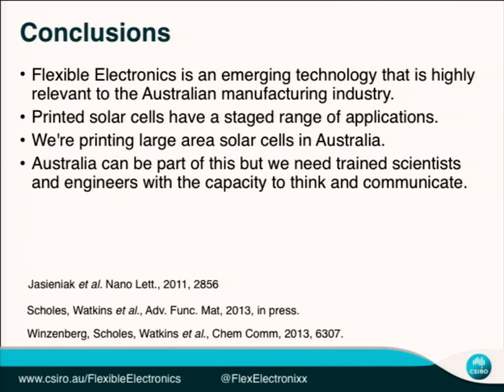Do you have any idea at this very early stage what the energy decrease is over the years? Silicon panels are about 12 years. I guess the only data that we've got is what I showed there, where we've got pretty stable current out over a year now. The degradation pathway that we're seeing tends to be catastrophic. So we've got a fairly low reduction in current and then a big drop off, and that's typically due to a mechanical failure, ingress of oxygen or water through the barrier material. But if we take OLEDs as an example, people have made OLEDs now with lifetimes of like 300 years. So I don't think there's a problem here. It's the same, an organic semiconductor that you're putting electricity through. So I'm pretty hopeful about that.